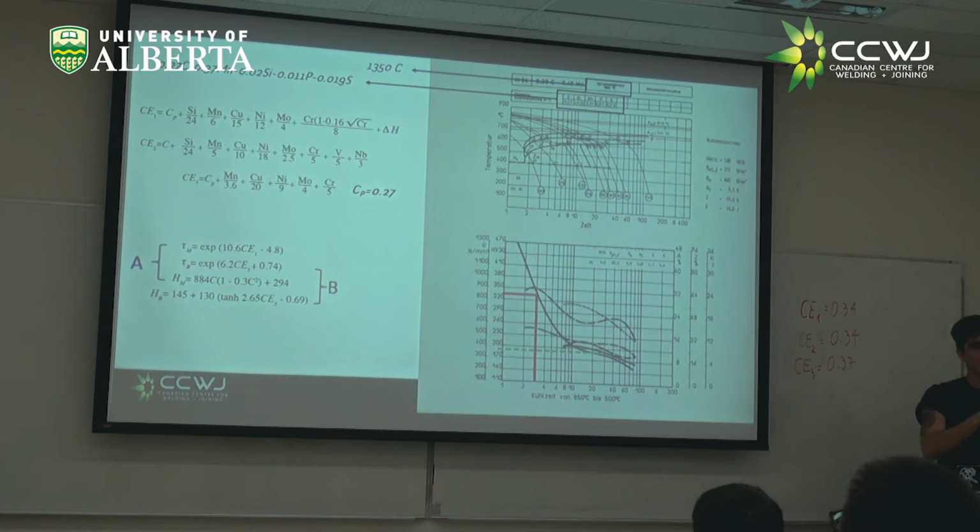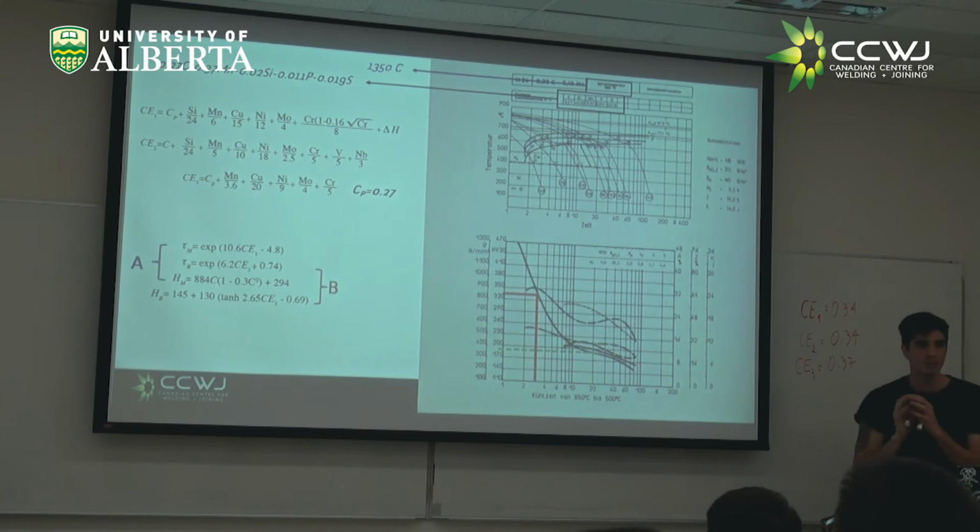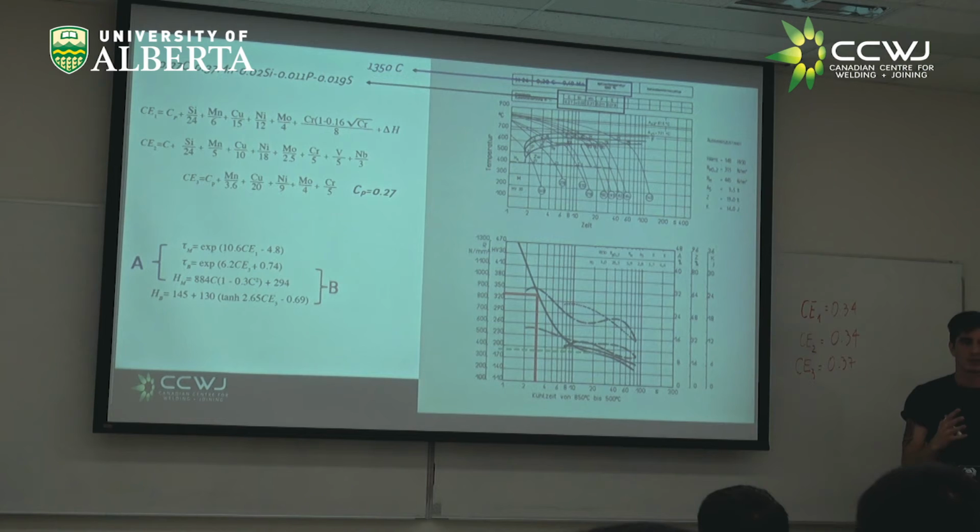Delta H value depends on the boron content, and that specific term is reserved for when steels have boron. The hardenability increases significantly, and the boron effect depends on the content of nitrogen, and a minimum amount of boron, like ppms of boron, can change hardenability drastically, right?